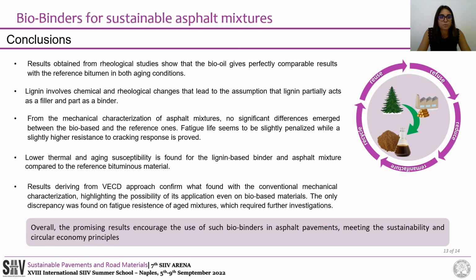Results obtained from rheological studies show that the bio-oil gives perfectly comparable results with the reference bitumen in both aging conditions. On the contrary, lignin involves chemical and rheological changes that lead to the assumption that lignin partially acts as a filler and part as a binder. From the mechanical characterization of asphalt mixtures, no significant differences emerged between the bio-based and the reference ones. Overall, fatigue life seems to be slightly penalized, while a slightly higher resistance to cracking response is proved.